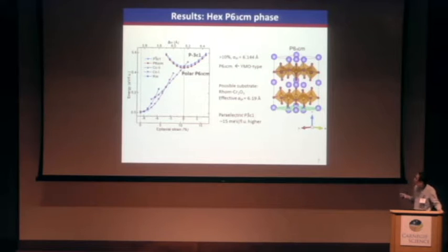Next, at even larger in-plane lattice constant, we notice that the hexagonal P63cm phase becomes the ground state. And you may be surprised that this epitaxial strain is more than 10%. But you may also notice that the local minimum is out of the curve of perovskite. So we think if this metastable phase is really synthesized experimentally, there should be no strain effect here.